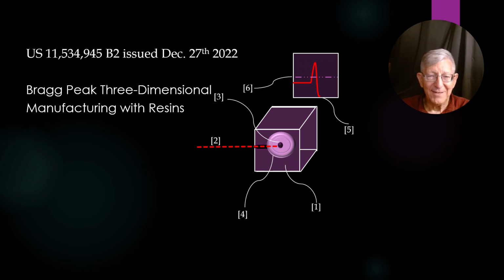And by setting the total dose number, that would be 6, that little horizontal line across the graph. If you set the total dose at a place where only the Bragg peak density of energy will cause the essentially catalytic reaction among the monomers that are turning into the polymers, then you can cause things to happen within the liquid resin.